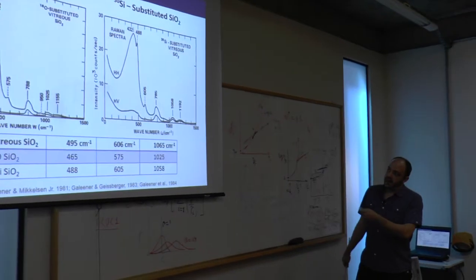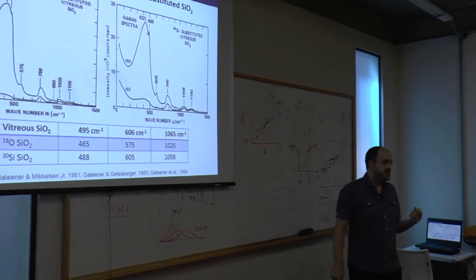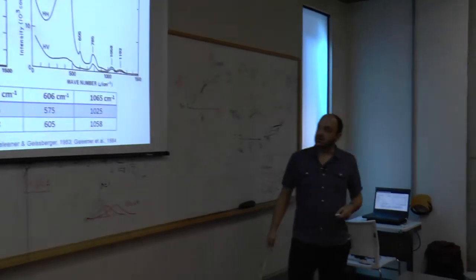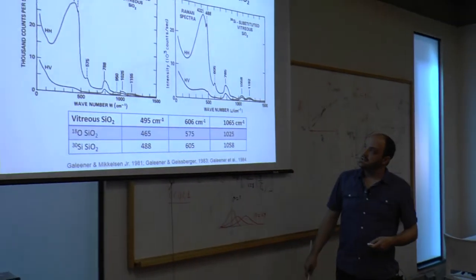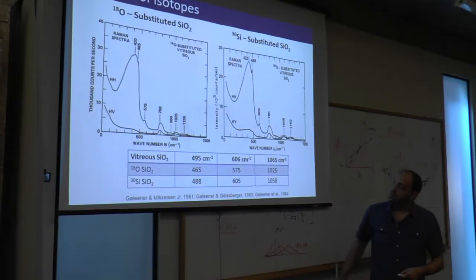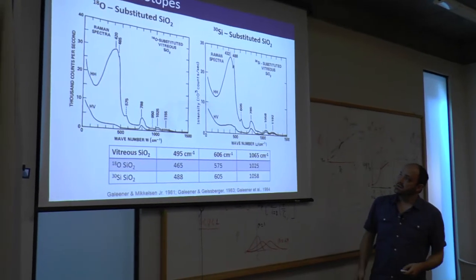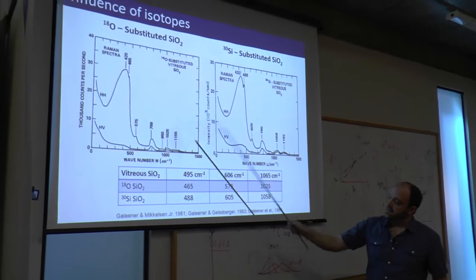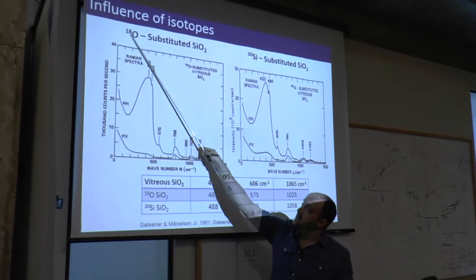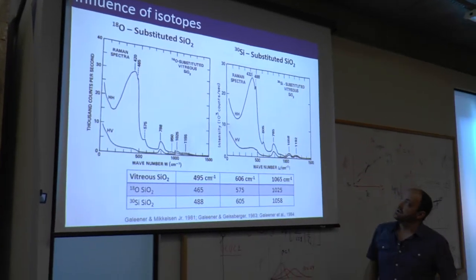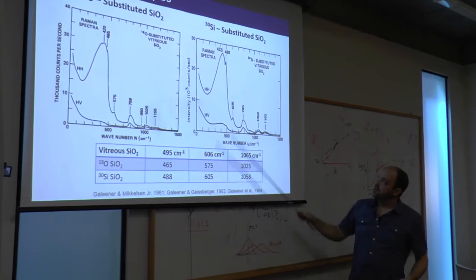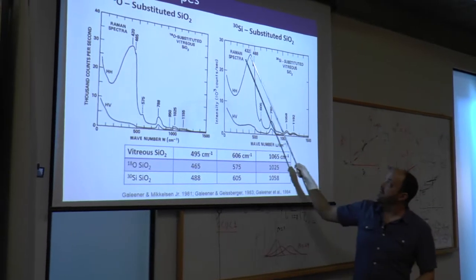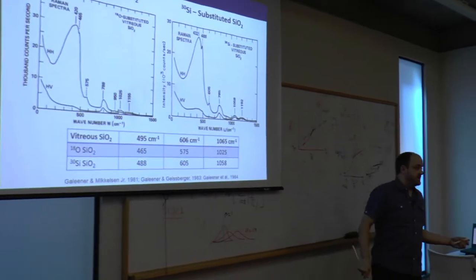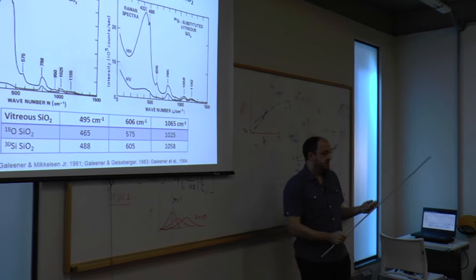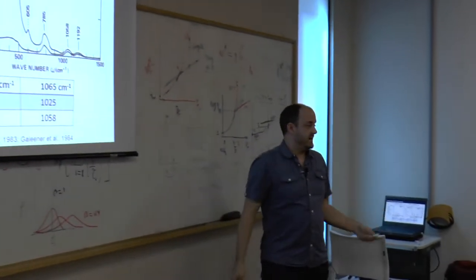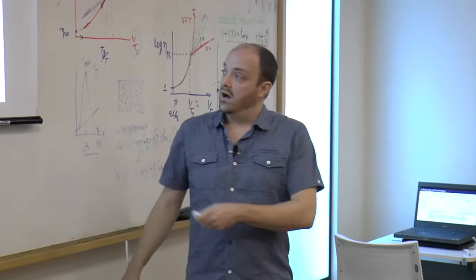This actual fact was what was used to identify some of these weird features in the silica spectrum back in the early 80s. This is that same spectra of SiO2, and again, don't worry about the assignments, we'll come back to them. But Galeener and co-workers substituted heavy oxygen and heavy silicon isotopes into the silica structure and looked at the shift in position of all these main features. This allowed them to identify whether these vibrational features are associated with silicon, oxygen, or some other defect or something else that's going on in the system.